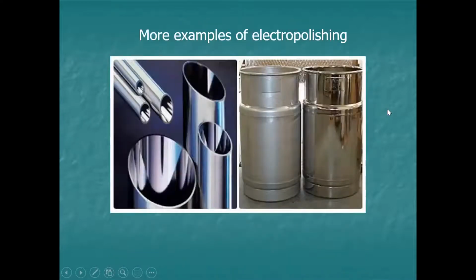Here's another example. Electropolishing is often used in the food industry in order to prevent the metal, especially stainless steel, from dissolving in the food and giving it a bad taste, and also to prevent corrosion. Because the whole point about the corrosion protection with electropolishing is that because it has a very smooth surface, there are very, very few defects in the surface which can start to form pits and therefore give rise to pitting corrosion, which, as you know, is the main problem with stainless steel.